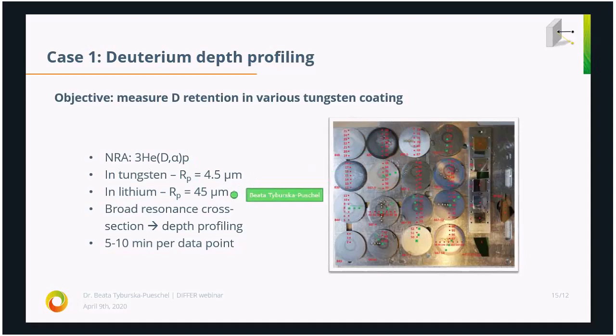But for example, we are performing deuterium depth profiling in lithium. Then you have a maximum penetration depth of 45 micrometers. The very specific thing about this reaction is that it has a very broad resonance cross-section, which enables us depth profiling. This is also a very fast technique. We usually spend 5 to 10 minutes per data point.